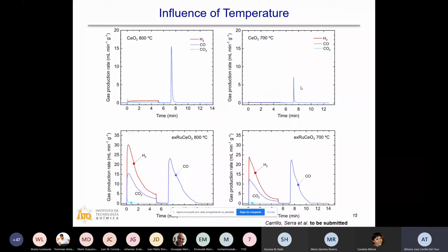If we lower the temperature for ceria, the amount of syngas reduces a lot, although there is still the creation of some vacancies that allows CO2 splitting in the oxidation step. Whereas for our material with the exsolved ruthenium nanoparticles, we observed that even at 700 degrees Celsius, there is a very interesting amount of syngas and CO2 splitting in the reaction.